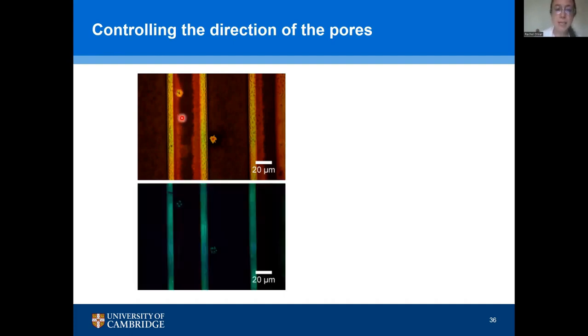Taking that into the polarized light way of imaging, we can see that we have these regions right next to that sidewall with this very, very bright contrast in the polarized light microscopy. And we have indeed, we think, and I'll show you how we know, managed to align the pores. We can also see one Maltese cross structure, which is radial etching, in this case, driven by the hole in our silicon nitride rather than necessarily by a big pit.